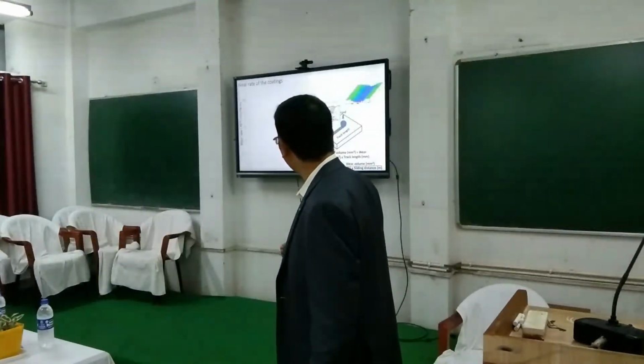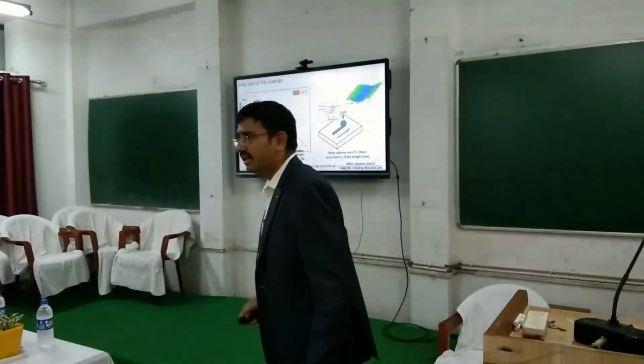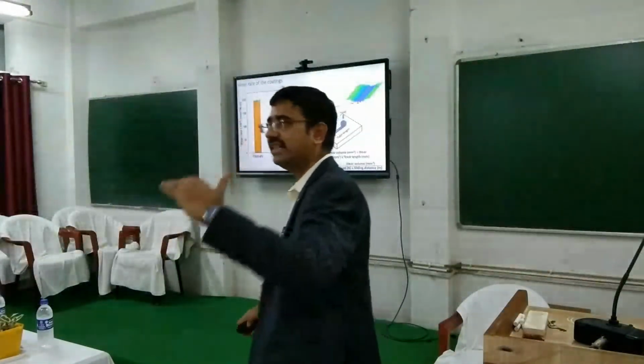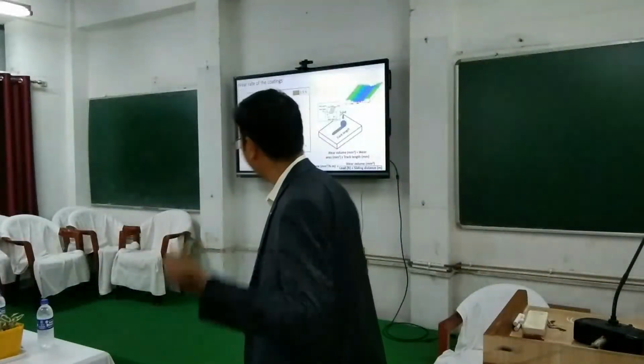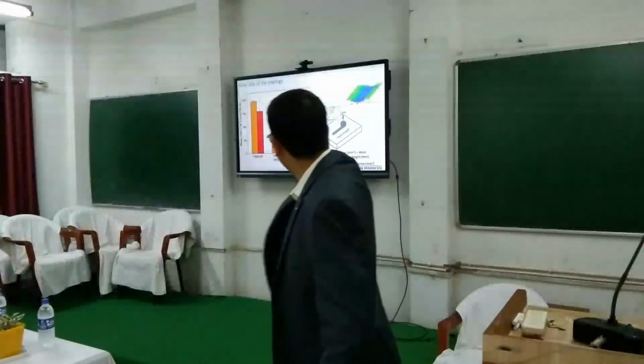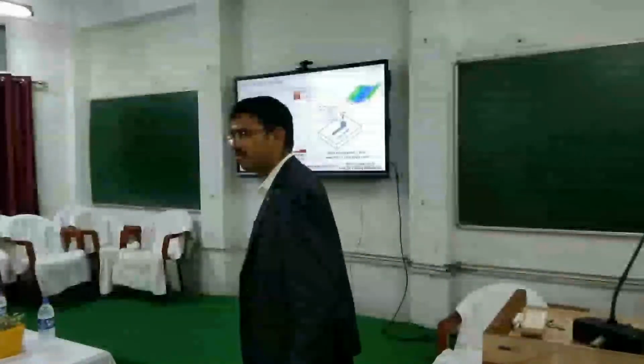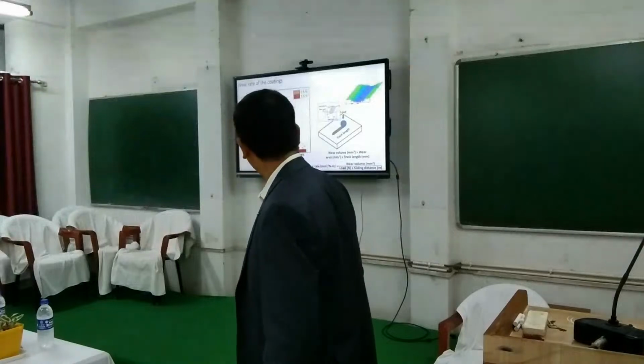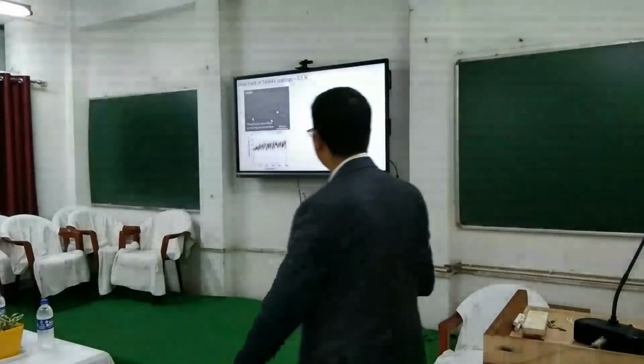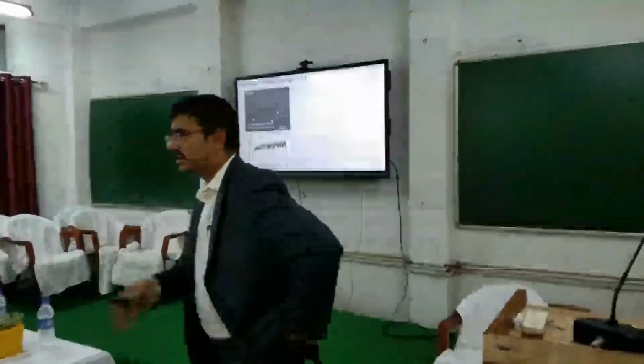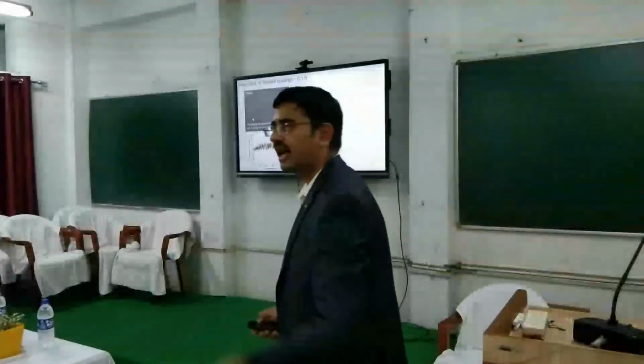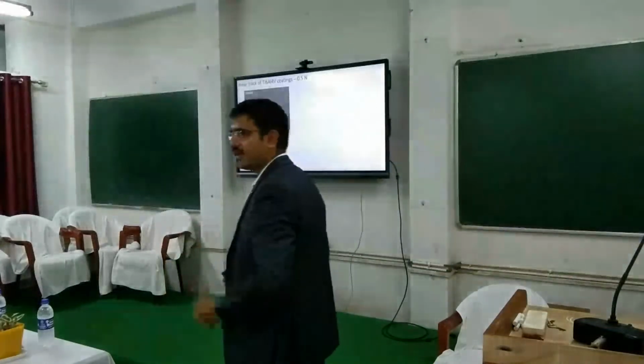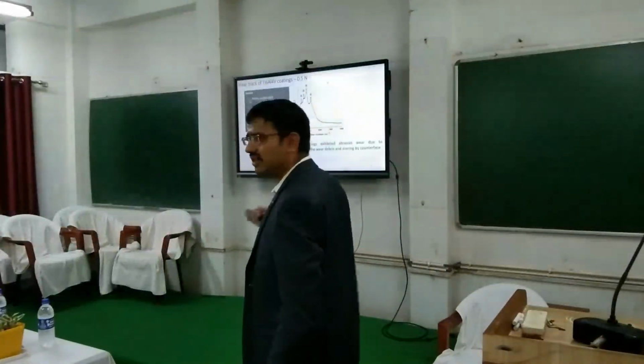After the wear test, we measured the wear volume and we calculated the wear rate. We observed that compared to titanium 64, the composite coating showed one-tenth the volume material removal rate. And even at higher loads, we could see that for the carbide coatings with the highest volume fraction, the wear rate is very low. To see why this phenomenon is occurring, we looked at the wear tracks. In the wear track of titanium 64, we could see abrasive ploughing. The oxide has formed, it has broken down, and it is grooving the material, and that is resulting in a highly fluctuating coefficient of friction and high wear rates. And these particles are mostly oxide particles.